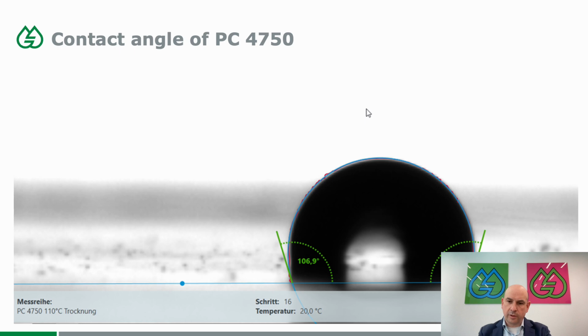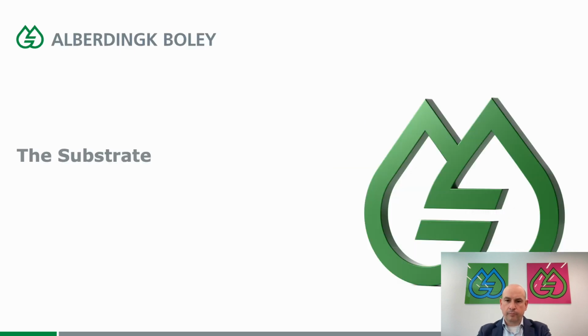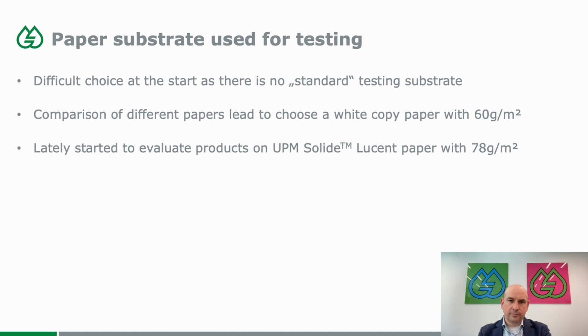We can also prove that if we look at the contact angle of the PC4750, you can see here that we are able to reach a contact angle of 107 or 108 degrees on paper. So that shows you how good and how hydrophobic the material actually is in such a low film thickness. Here we are talking about a 6 microns drawdown. If we now look at the substrate paper, which is not as easy as one would think, what kind of paper did we use to test?